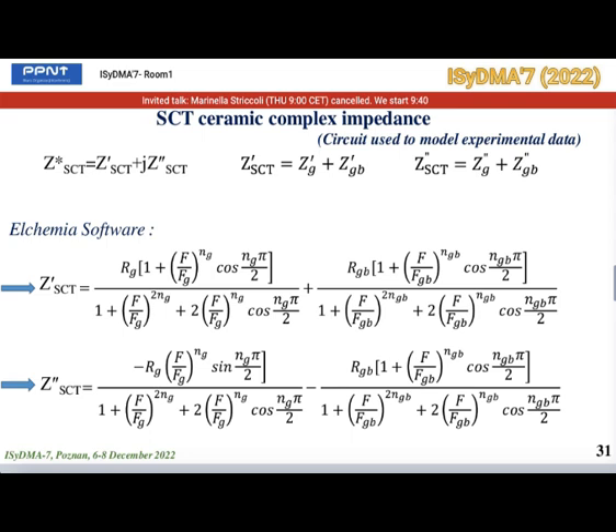Concerning the real and imaginary parts of the ceramic's complex impedance, they are calculated from those of grains and grain boundaries according to this formula, followed by further mathematical formulas, in which the different elements are calculated by Elchemia software.